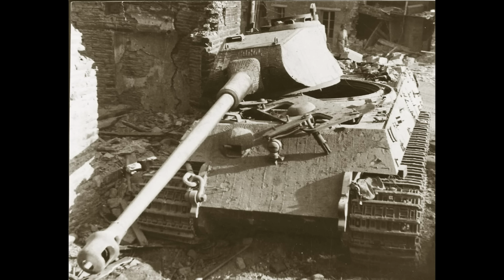The projectile's hardened steel penetrator encountered first the martensitic surface layer, 15mm of extremely hard crystalline structure that resisted initial penetration, abrading the penetrator's tip, creating heat and friction that began degrading its penetration capability. Then the bainitic core, 87mm of tough crystalline structure that absorbed the penetrator's kinetic energy progressively, creating microcracks that dissipated impact forces without allowing catastrophic crack propagation. The penetrator fragmented approximately 60mm into the plate, its remaining energy insufficient to complete penetration.